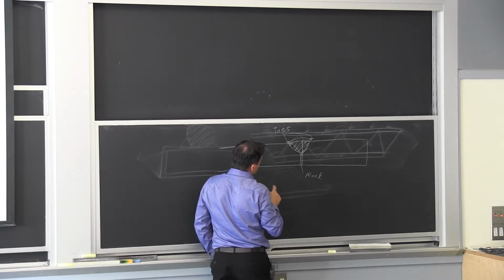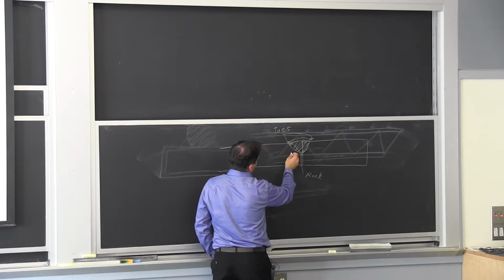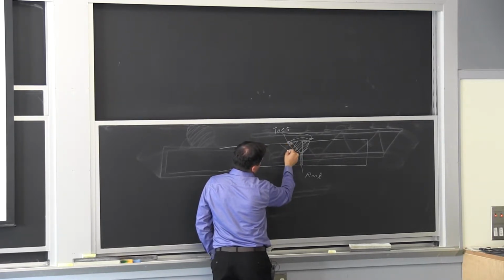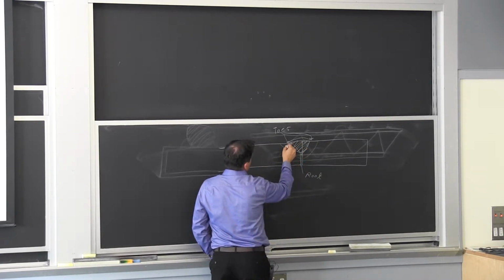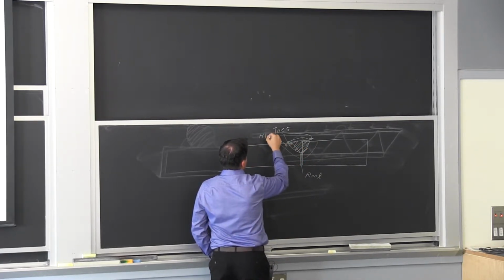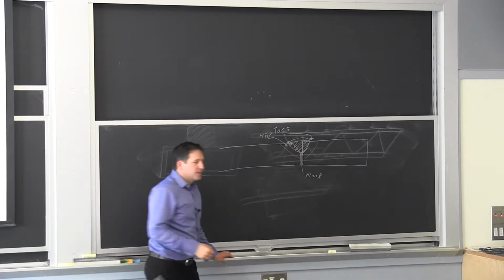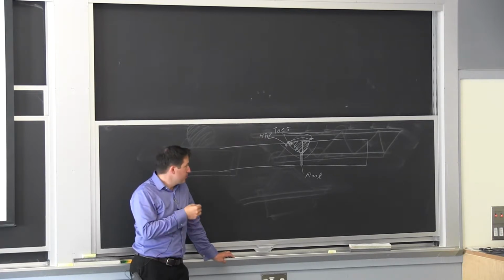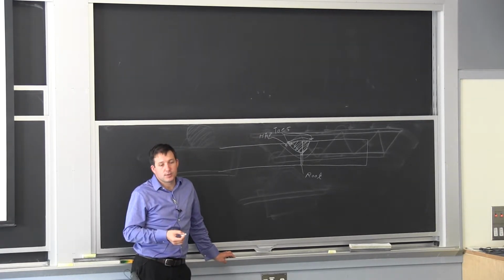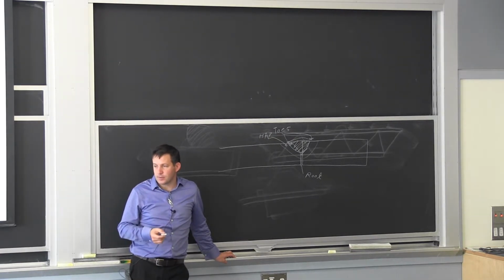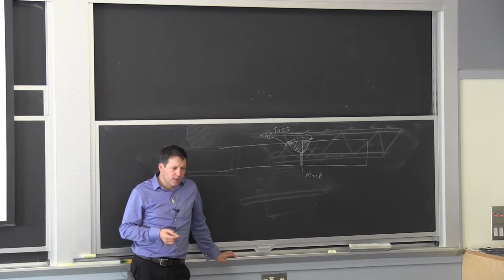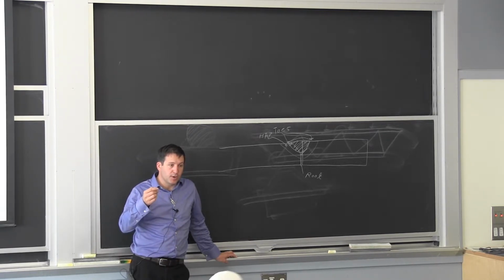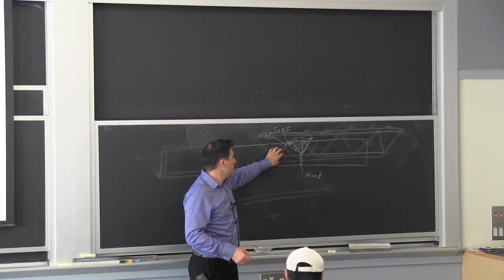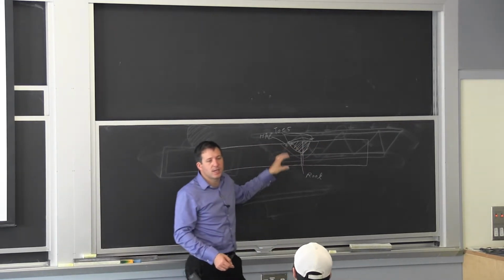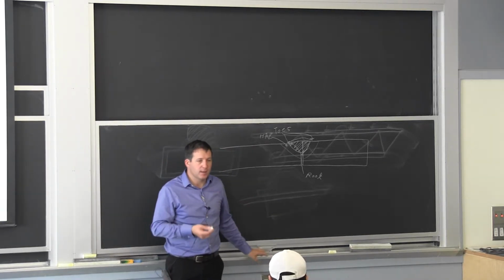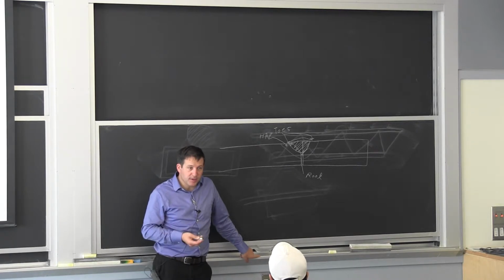And the thing that we need to start talking about today is the heat affected zone. The heat affected zone essentially starts in a portion that's not melted. The abbreviation for it is just HAZ. Any metal, it could be aluminum or steel, they both have a heat affected zone. That heat affected zone is very different. If we think about steel, I'm heating it up and I'm going to quench it, because when I heat it up quickly and then cool down, I have all that mass of steel on each side to pull the heat away and give you a very fast cooling rate. So it's very similar to quenching.